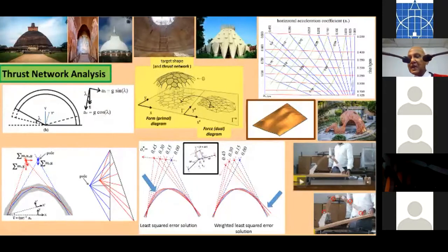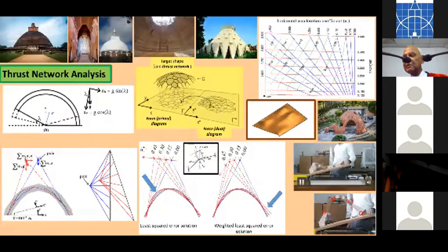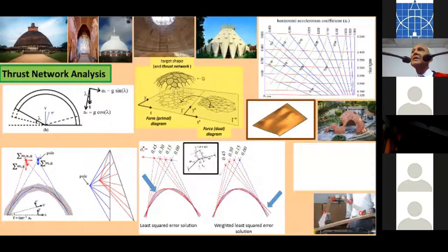So this is a small experiment that is carried out to indicate that with this kind of thickened arch, we can reach angles of tilt that are quite significant. You can see this is not taking any tension because this is made of every individual block. You can see all the blocks collapse, meaning it cannot take tension. But even though it cannot take tension, it can take a considerable amount of tilt, or in fact horizontal load.